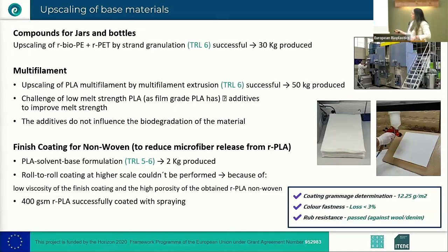First, we thought to use a roll-to-roll coating at higher scale, but we saw some difficulties in matching this coating with this technique, but it doesn't mean that this coating cannot be used with another technique. Then again, if we want to make a change, we have to rethink things. Therefore, we went for another solution. What about we use this coating, but we spray? And we successfully did the production of this coating application on these nonwovens made of recyclable PLA.